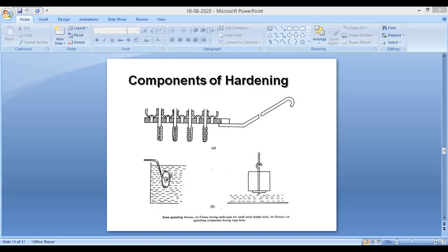Holes in components and tools have an increased tendency to cracking, particularly when water quenched, as hardening occurs first there. Such holes may be packed with wet asbestos, clay, or steel inserts to avoid hardening inside them. Threaded holes are blocked by screw plugs. Many times, special fixtures are made to hold the heated parts to be immersed in the cooling tank to avoid distortion. Small-sized parts are often put in pans or on iron sheets to be heated and then simply poured into the cooling tank, which already has an immersed netted basket for easy withdrawal from the cooling tank.